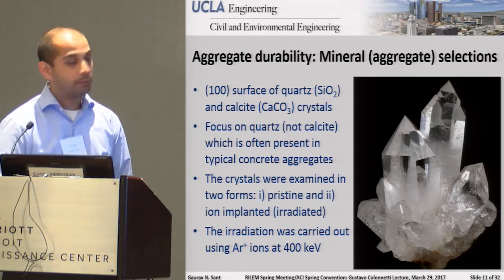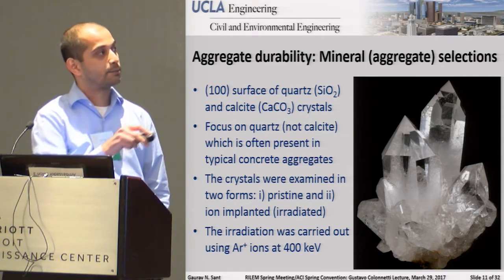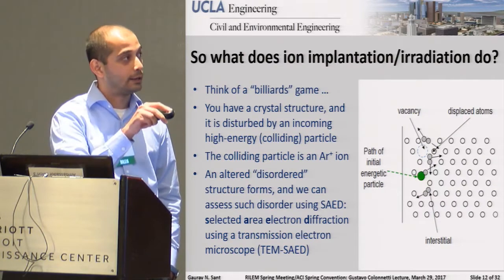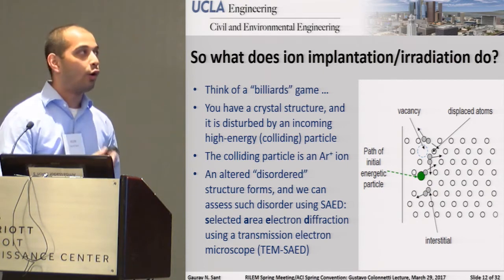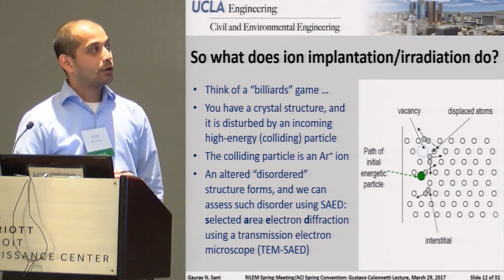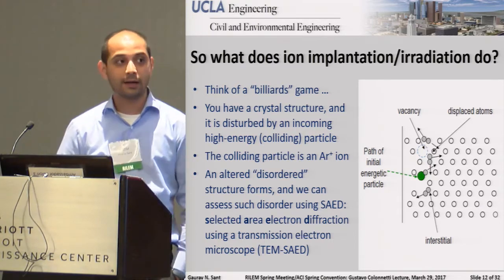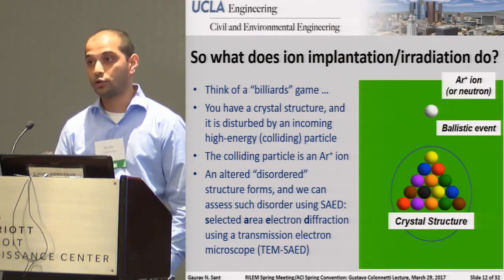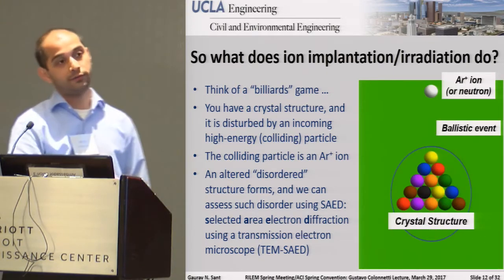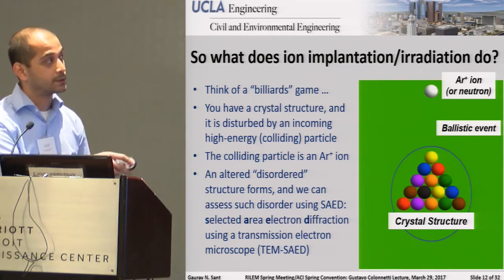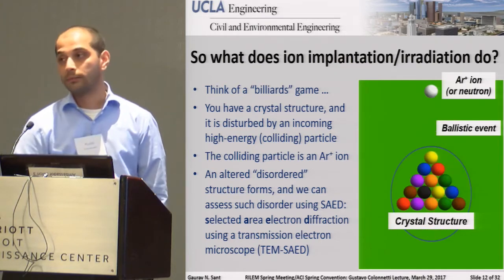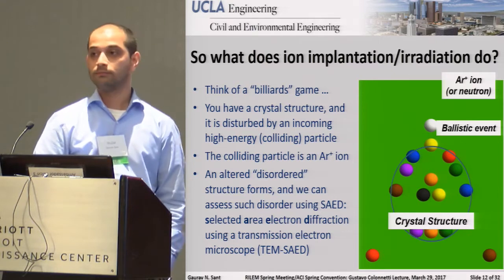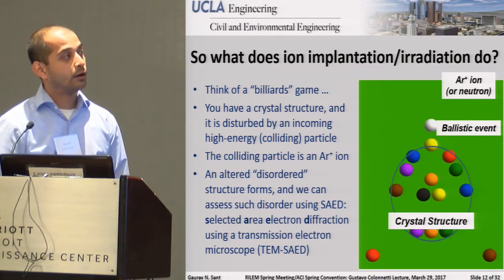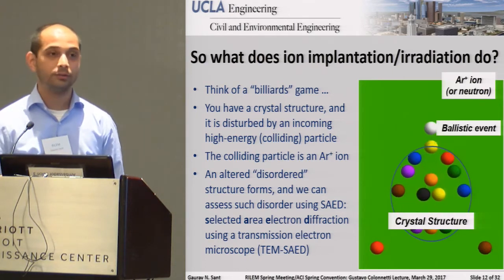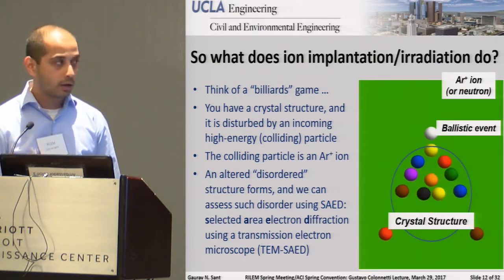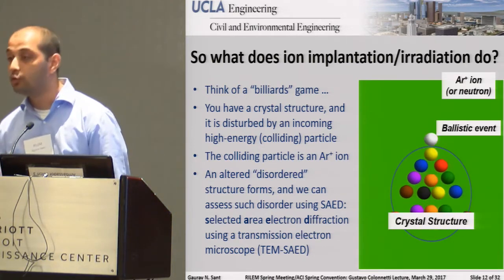Now, if you really think about what ion implantation or irradiation does, I can explain this two ways. I can explain this with an ordered crystal structure and tell you there's an energetic particle, and I can tell you the things move, and you can cause vacancies, and you'll get displaced atoms. Or I can go back to a game I played many years ago. If you start to look at the idea of billiards, you've got an incoming particle that's accelerated towards an ordered structure. Your ordered structure is, of course, a crystal structure. And you can start to tell as you transfer kinetic energy from an accelerated particle into a crystal structure, you get displacements. An important thing to note is that you're getting quite a bit of disordering. So what was originally a very ordered case now looks very disordered. The nice thing is you can ascertain this kind of disorder using what's known as selected area electron diffraction. You do it within a transmission electron microscope, and you can really start to tell very closely where the original atoms were and where they may have moved, as an example.